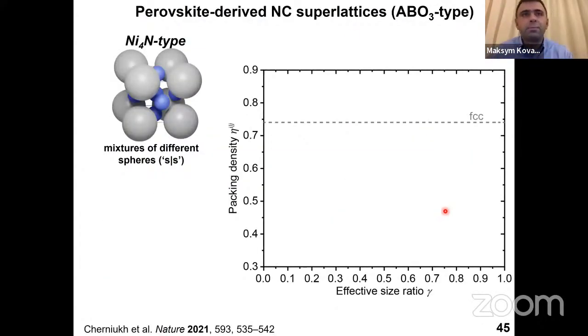And let me show you one very prominent example of such a crystal structure. Look at this mixture of two spheres, which I already tell you had never been observed experimentally. So only atoms form this crystal lattice, but nanocrystals, at any size ratio, two spheres never crystallize in this crystal structure. This is the nickel-four-n type lattice, which is basically derived from the perovskite lattice when the facet and the center atom is the same.